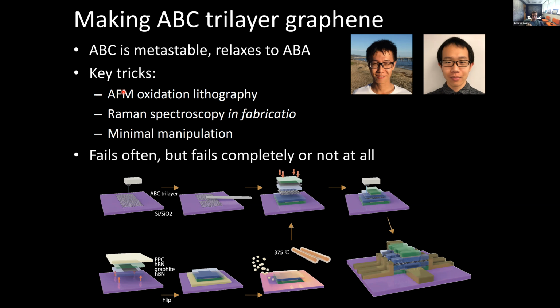So you can cut out purely ABC flakes. That actually helps because that will prevent these ABC domain walls from propagating if they hit just an edge of a graphene flake. You do Raman spectroscopy throughout the process, so we design our whole process so that we can abandon samples that have already relaxed to ABA, and we develop some tricks for minimally manipulating these ABC flakes.